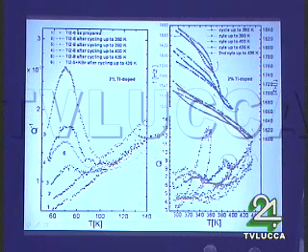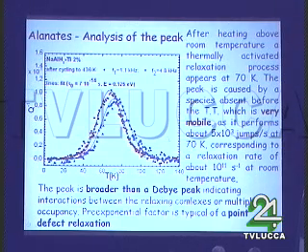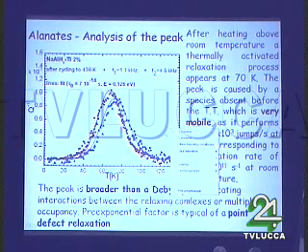After each high temperature measurement, we carried out the low temperature measurements in anelastic energy dissipation and modulus. So after the cycle not displaying decomposition, the dissipation decreases monotonously. But after decomposition, we observe the development of a peak which increased and developed with increasing high temperature treatments. So this peak is rather surprising.